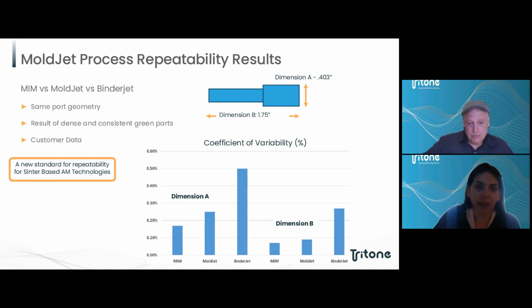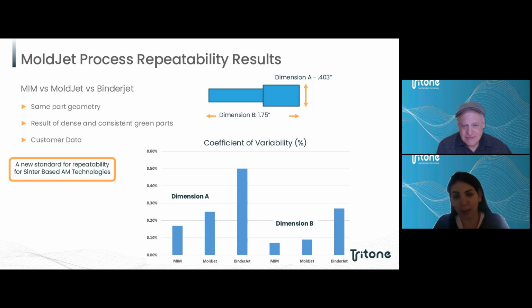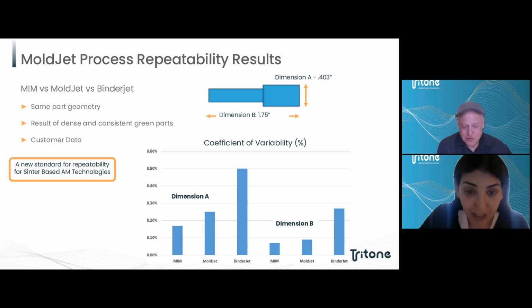And the other thing, you mentioned the strong green parts. I think that's also within sinter-based a really unique differentiator that might be worth pausing on, because I know, hearing from customers and additive users who use other binder jet technology, the green parts tend to be on the weaker side, they often break before even going into sintering, meaning if you need, let's say, 1,000 parts, you're not actually printing 1,000, you might be printing 1,200 or 1,300 parts to ensure that you get 1,000. Sounds like that's not an issue here.